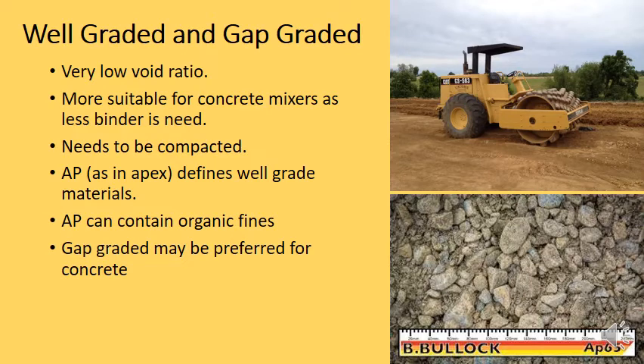Now the other thing with well-graded is that sometimes they make well-graded with something called apex, where they put the aggregate through a sieve. You can see in the bottom corner there, Apex 65, AP65. That means they've put it through a sieve with an opening of 65 millimeters, so anything smaller than 65 millimeters is inside that aggregate.